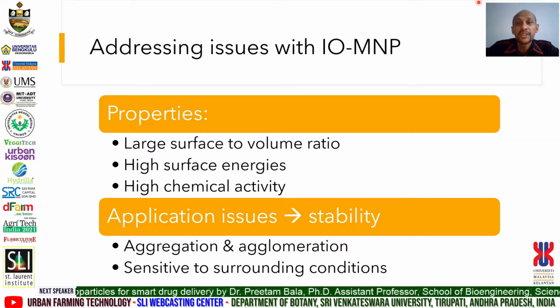Agglomeration makes separation difficult. Depending on the ultimate purpose of use, magnetic nanoparticles on their own are less suitable as adsorbents. These are clear limitations of using iron oxide magnetic nanoparticles in their free form. In order to optimize the synthesis of iron oxide nanomaterials in larger volumes, surface modification and medium modification are required. This modification could help produce stable magnetic nanoparticles which can resist oxidation and prevent self-aggregation.